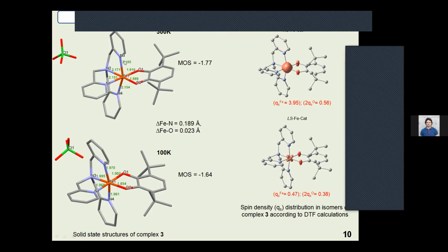The MOS parameter for 3 amounts to minus 1.77. Significant changes of metal-donor atom bond lengths were found in complex 3 collected at 100 Kelvin, caused by high spin to low spin conversion. Spin transition is accompanied with the shortening of the characteristic interatomic distances.